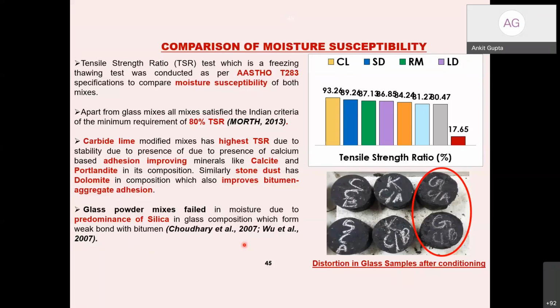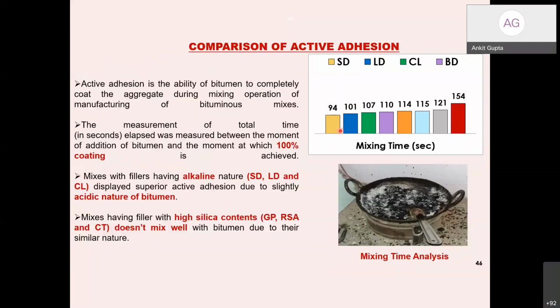So we can use some percentage, like 3 to 4% of the glass dust and 2 to 3% of the carbide lime. It becomes a good filler, although it has some limitations in application in the field, because who will do that controlled mixing in the field. But we are trying to find solutions for that also. So still, in most things the glass powder is giving satisfactory results, but only for the moisture part it is failing. Now comparing with the active adhesion part.